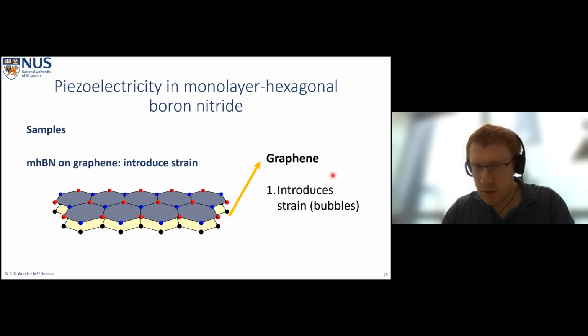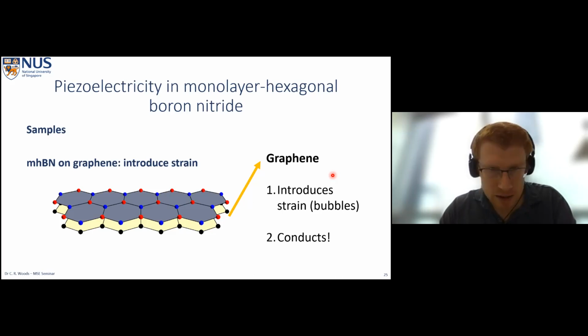The second reason to use graphene is because it conducts electrons. And so if we have an induced charge in our monolayer boron nitride layer, we can expect that the electrons in graphene will see this charge and move accordingly. So these are two reasons to use graphene as our adjacent layer.